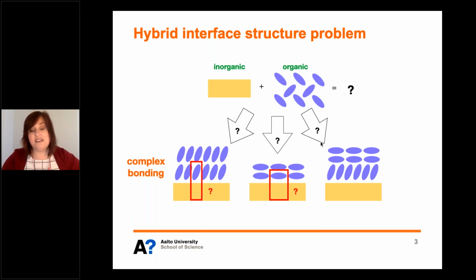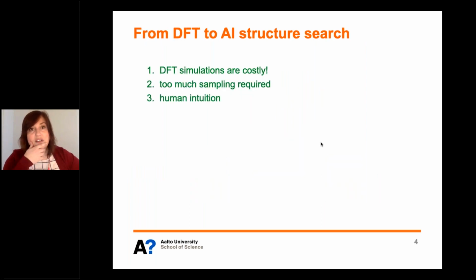So the first thing we have to do is DFT-based structure search for molecules and surfaces. And there are lots of problems with DFT structure search. Our simulations usually involve many atoms, quite large molecules, big chunks of substrate, so they're pretty costly. I mean, we run them for days or weeks. In order to know which structures are the most relevant and stable, we need to look at many different structures, so there's a lot of structural sampling involved. To avoid this, what people typically do is use intuition to guess what structures might be viable, but this is risky because you never know if there are other structures that might be even more stable. We just didn't think to check them.